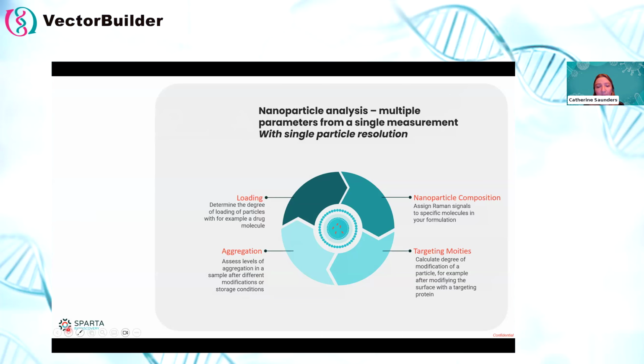So what parameters can SPARTA tell us specifically? Well, because we measure the full Raman spectrum of individual particles, we can measure these multiple parameters simultaneously with single particle resolution. This includes nanoparticle composition, such as cholesterol and ionizable lipids or protein content, targeting moieties, such as proteins or sugars, the degree of aggregation, and the amount of loading, for example, of RNA per particle.